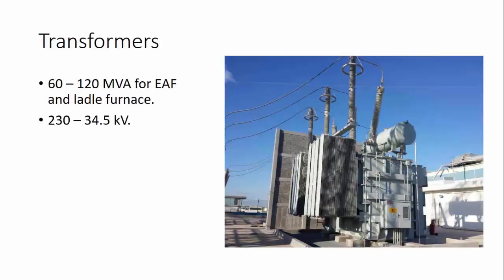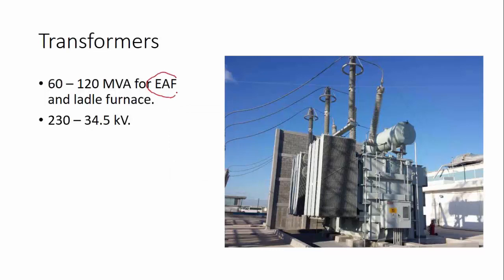So the next thing we can find is generally a pair of transformers. One is intended for the electric arc furnace and it's a huge transformer, and right next to it you will find another transformer which is for the rolling mill. Now this transformer is for the electric arc furnace which melts the steel. And then we have some ladle furnace. A ladle furnace is also an arc furnace, but much smaller, and the steel is refined in that furnace. It's not molten because it's already molten from here, but the steel is refined in the ladle furnace. They add oxygen, carbon, nitrogen, whatever it takes to make the desired steel with the desired properties.